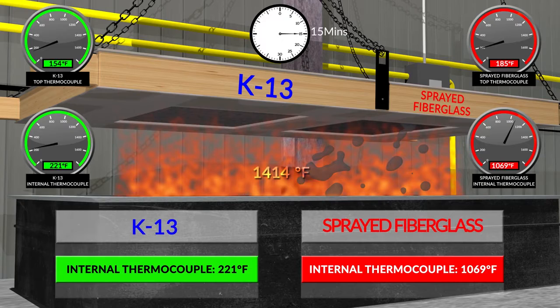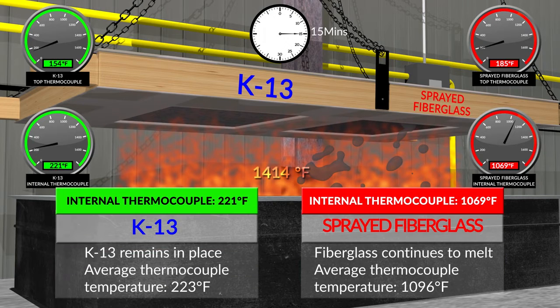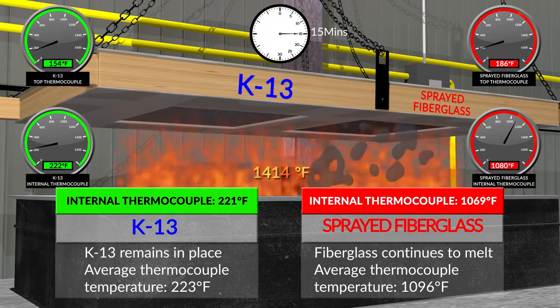At 15 minutes, K-13, the internal thermocouple is 221 Fahrenheit. Sprayed fiberglass, the internal thermocouple is 1,069 Fahrenheit. K-13 remains in place. Average thermocouple temperature is 223 Fahrenheit. Fiberglass continues to melt. Average thermocouple temperature is 1,096 Fahrenheit.